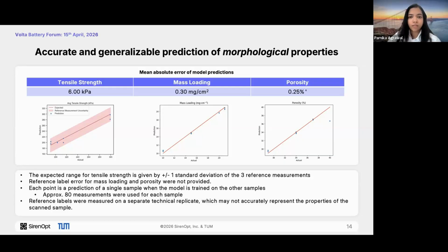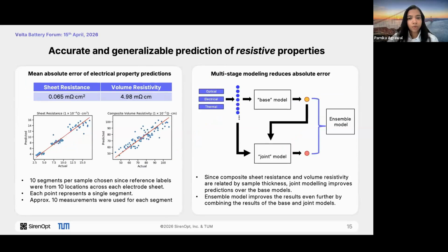Sure. Thank you, Johannes. As Johannes mentioned, other than mass loading, all of the other properties were measured offline for reference measurements, and we were able to calibrate and get very good performance with very low mean absolute error across several properties. This slide focuses on resistive properties. The tool used was shown two slides ago, a Hioki tool that gives out multiple different resistance values, including sheet resistance and volume resistivity.